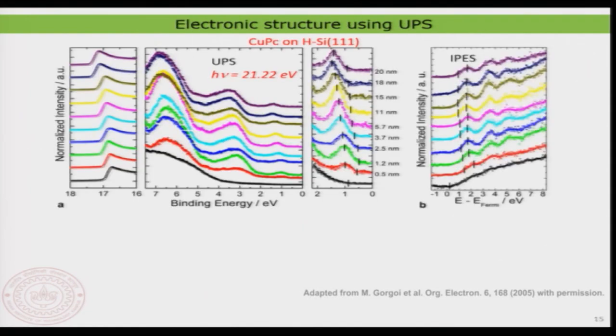And I have here a molecule known as copper PC, a copper phthalocyanine molecule deposited on a silicon 111 surface. And here is a UPS measurement carried out as a function of thickness, and also an inverse photoelectron spectroscopy measurement carried out as a function of thickness. What you clearly see is that as the thickness increases, the onset of the density of states of the valence band is shifting away from the Fermi energy, and similarly the onset of the conduction band. So this is representing the conduction band, and this is representing the valence band, and the onset of the conduction band is also bending in this way.